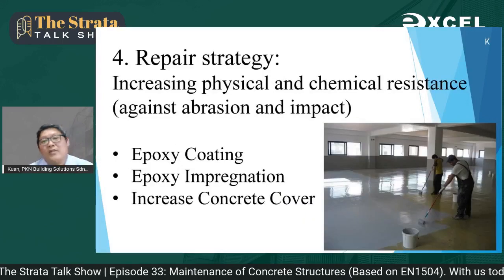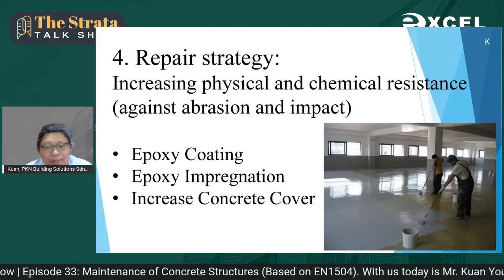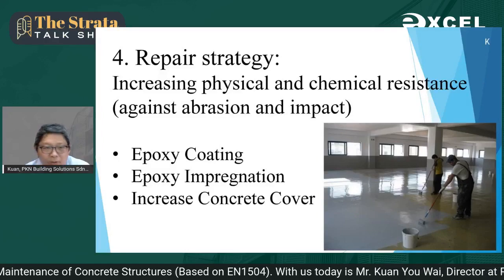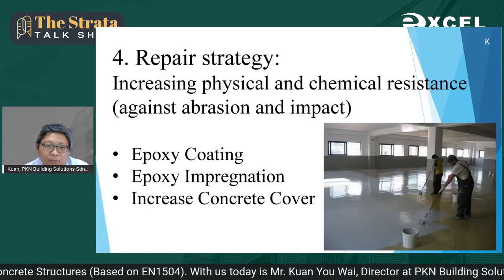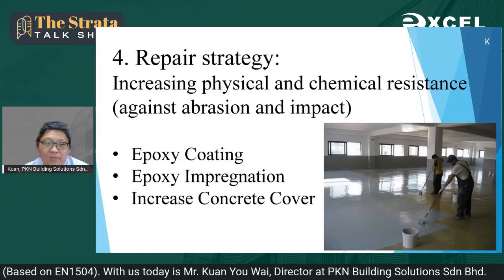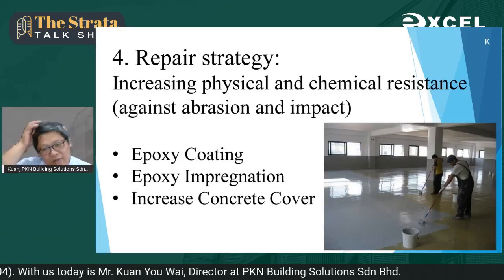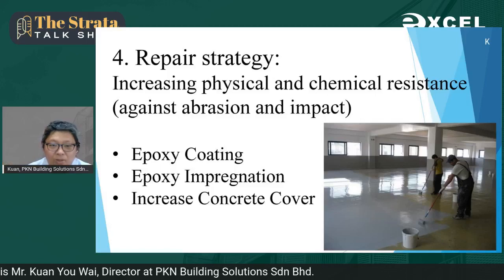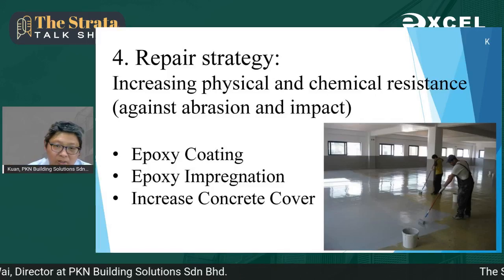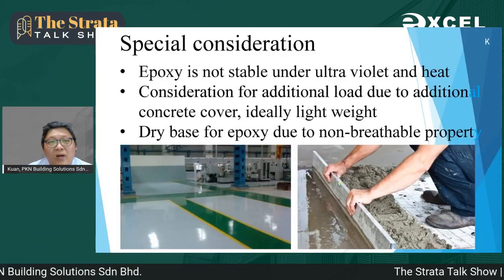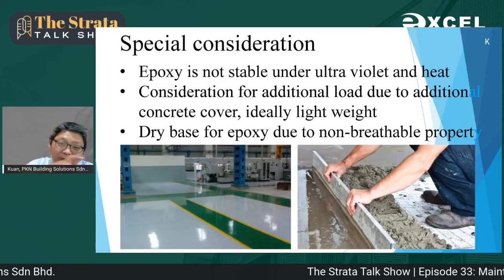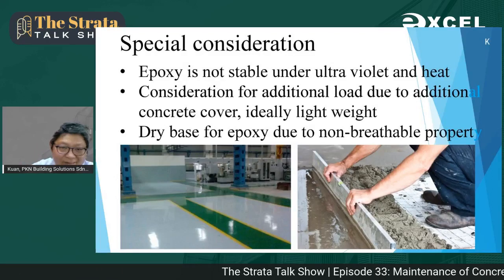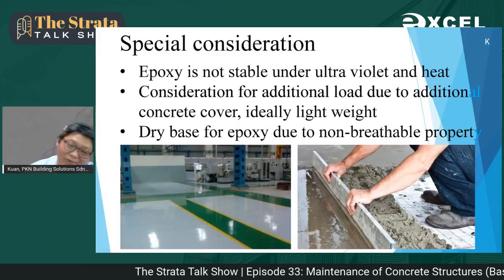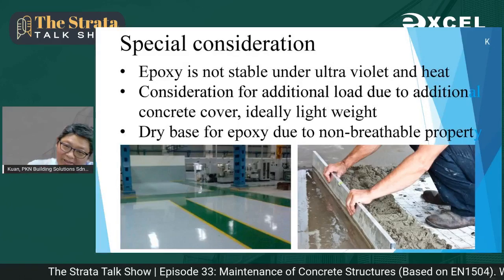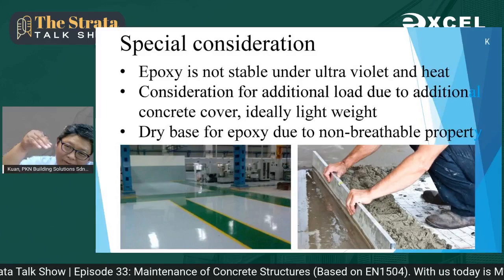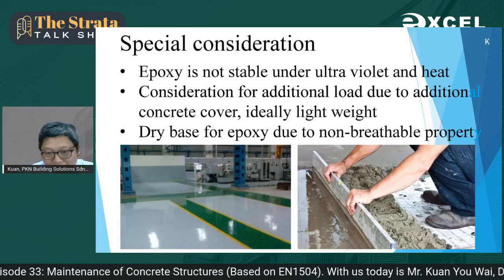And of course, if we apply coating, PU coating, epoxy coating, this repair strategy can reduce the diffusion of carbon dioxide as well as water into the structure. And of course, another way is to increase the cement screed. So when you increase the cement screed, of course, the water and the air cannot easily diffuse into your concrete.